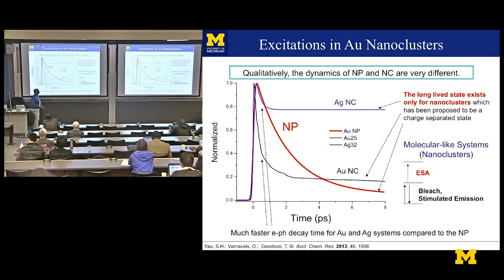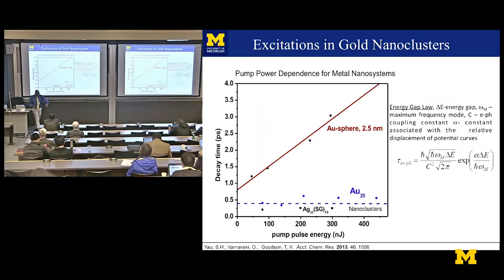You want to look at the time. So in terms of the time, here's the big particle again. That's what I just talked about. And then here's the small nano cluster. It's much faster in this region, and it has this decay. Okay? So what does this mean? Again, I increase the power. I increase the temperature, right? I turn up the juice. That should make the lattice vibrate stronger and take longer to cool, right? And this is what you saw in the big particle, it's the red. But in the case of the cluster, there was no dependence.